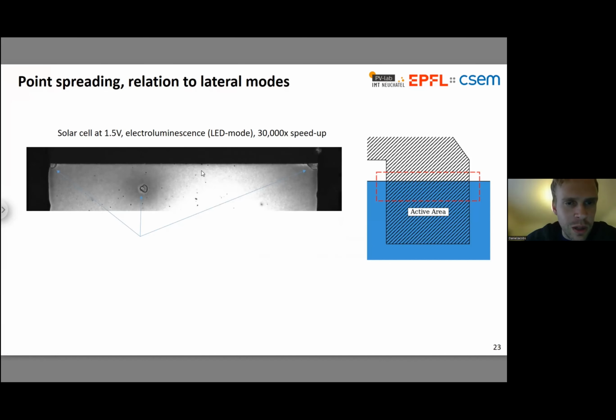I think it's quite interesting to see that this mode of ion-induced degradation is apparently connected to other forms of degradation that we're perhaps more familiar with. It's been described a few times now in the literature that perovskite devices have this tendency to degrade around points and in a propagating fashion, which is quite bad news. If you have one bad spot on your device, then very often it'll be a source of degradation that affects the surrounding areas, and you have this propagating front of bad stuff happening to your device.